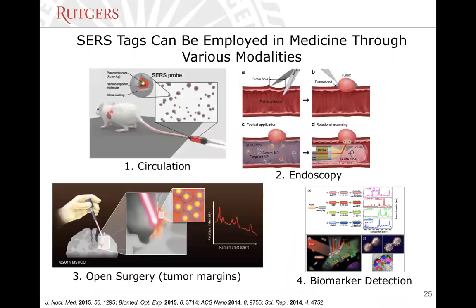Some people use them in circulation, although we know very well that the delivery of nanoparticles in vivo is not very efficient. We get up to 99.5% of particles excreted by the body, so it's not very efficient. What you can do is use them through endoscopy. Let's say you want to have a colonoscopy done, and you can inject the particles first as contrast agents. They will bind to any tumor that is present on the tissues of the colon. And then you use an endoscope with Raman capabilities to look for the SERS signal of these nanoparticles.